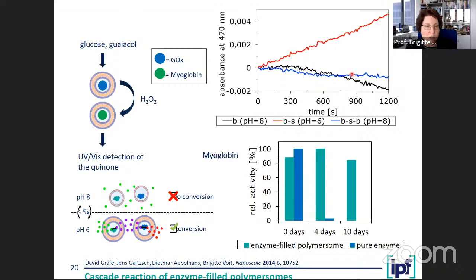Now you will say, why is it important? Actually, there's a huge need for having active enzymes also for a longer time. When you have the enzyme in such a controlled environment like a polymersome, the activity of the enzyme can last much longer. That's especially of importance for biotechnology, where you use enzymes for really technical production of products. So you can see here, when we have the enzyme in the polymersome, we can keep the activity for 10 days. It was studied here for 10 days. Whereas when you have it in the pure state, not encapsulated, after 4 days there's nearly no more activity existing. This is shown for quite some well-known enzymes.